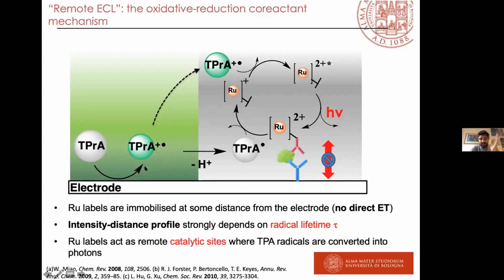And this potential is typically 1.1, 1.2, while the standard potential for TPA is 0.9. So you have a sacrificial coreactant and a catalytic cycle. This, of course, strongly depends on the TPA radical lifetime. So the radical lifetime really affects the emission at different distances from the electrode surface. This is a catalytic cycle.